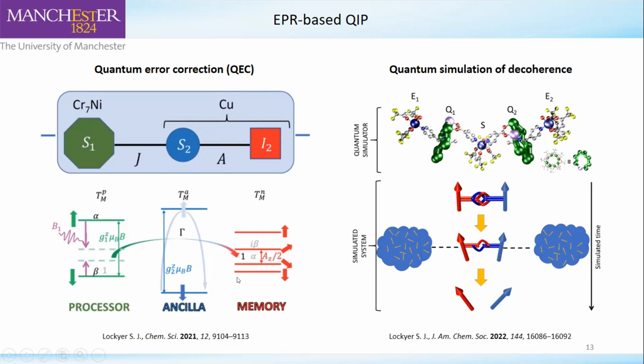It has been shown recently by our group, and this was published in JACS a few months ago, that we can probe the simulation of decoherence on an entangled state of these chromium-7 nickel rings. So I'll describe this in the next slide, but we can look at how these copper spins, so the blue are copper and the green are rings, can cause decoherence of the chromium-7 nickel ring entangled state. And this was shown as how much error in a quantum teleportation experiment actually evolved over time.